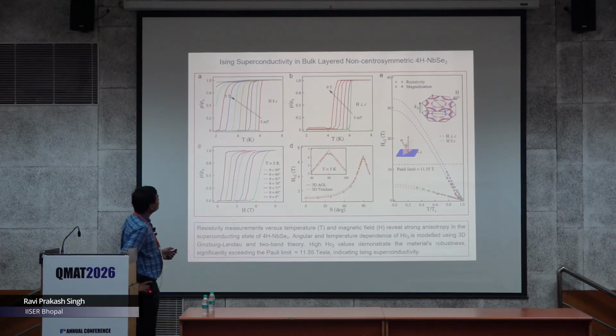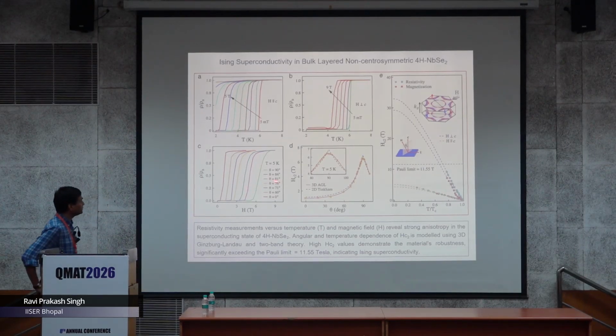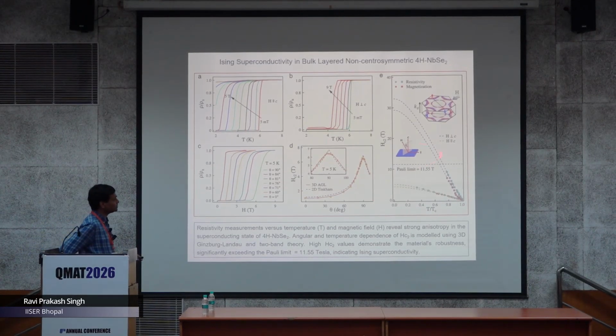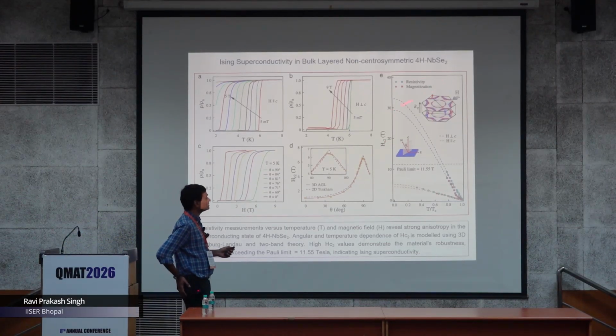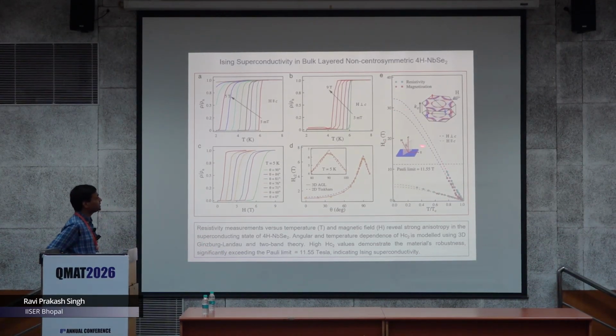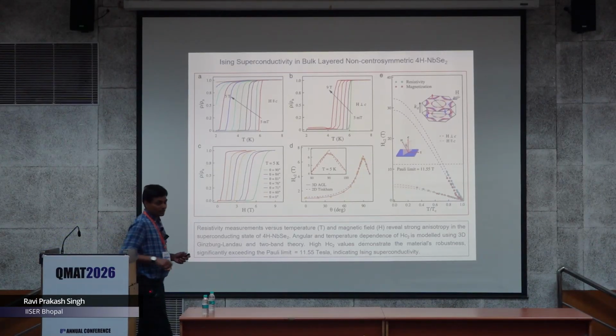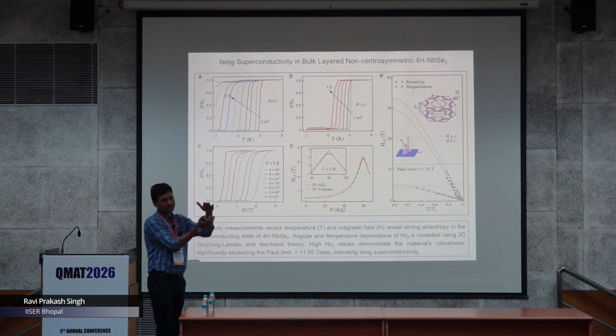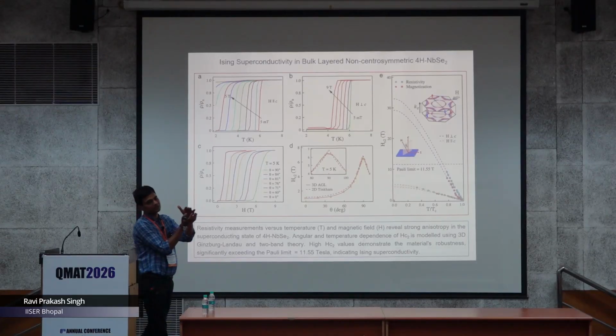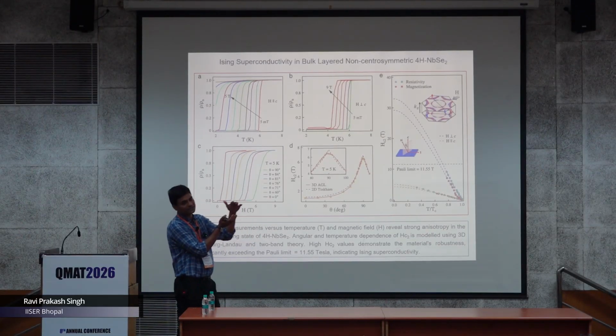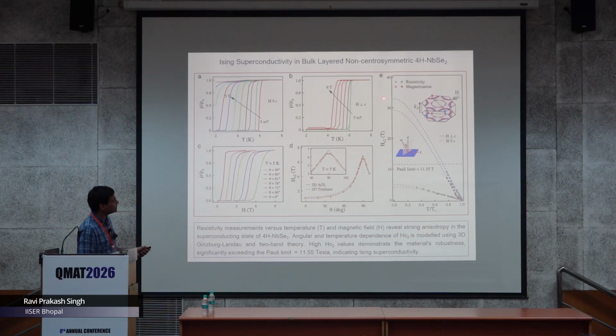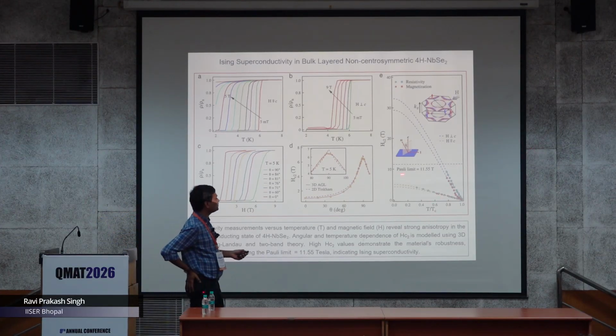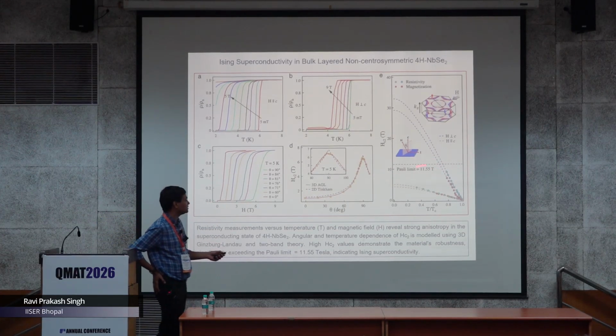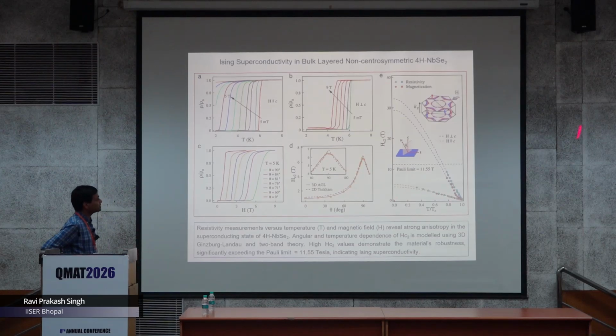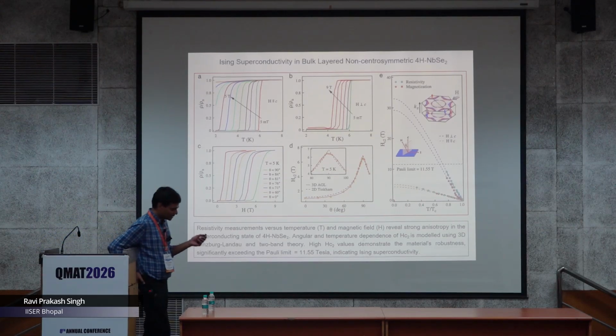But when we measure the Hc2, the upper critical field, you can see that by resistivity, magnetization and heat capacity, we are getting around 30 Tesla. And that is even in the bulk system, a 3D bulk crystal, where there is still interlayer coupling. Still we are getting around 30 Tesla, and the Pauli limiting field is around 11.5 Tesla. So it was clearly indicating that Ising type superconductivity is present in this one.